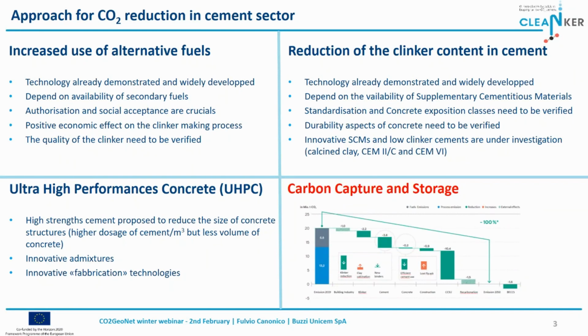We are also working on, let's say, eco-design, so proposing high-strength cement, very high-strength cement that could resize the structure, so lower the size of the structure using less volume of concrete, even with a higher dosage of cement per cubic meter. But of course, at the end, we will be able to save quite a lot of cement and clinker. And of course, a very important topic for us is carbon capture and storage.